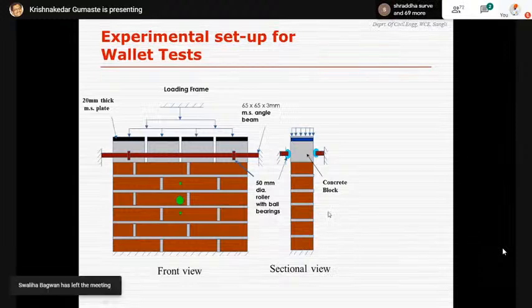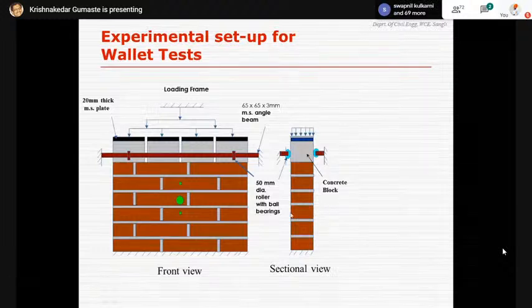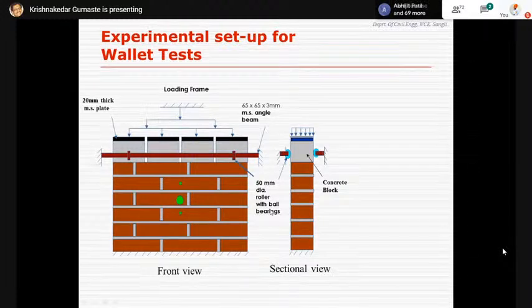So based on this kind of data, when you look at the experimental studies of compressive strength, wallets are recommended by the British standards, whereas in Indian standards, it is the prisms that are recommended for testing the masonry strength. This is one of the setups to assess the wallet strengths, where high strength masonry probably needs to be supported laterally so that there is no toppling over, or buckling of the masonry, when it is actually compressed.